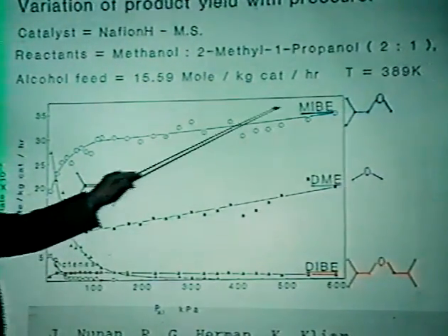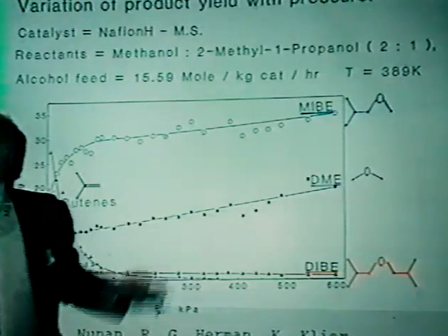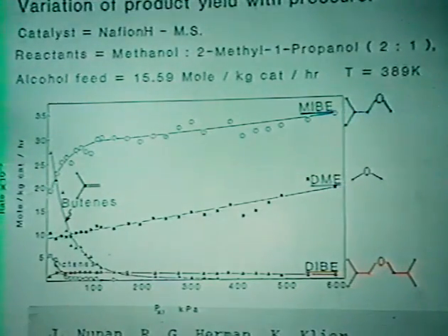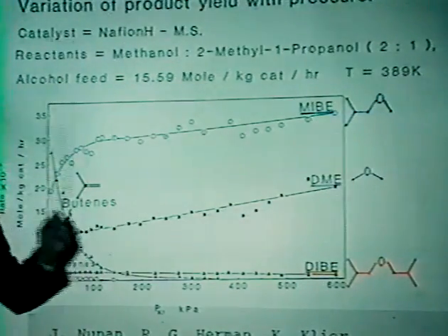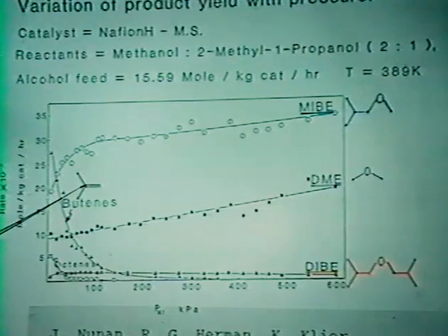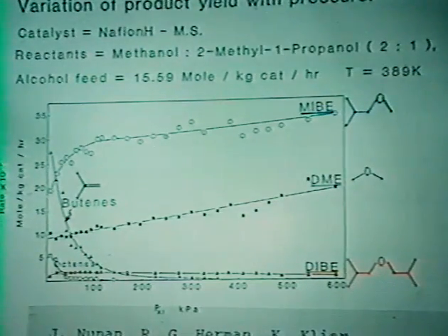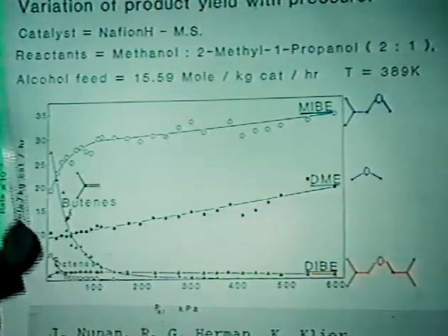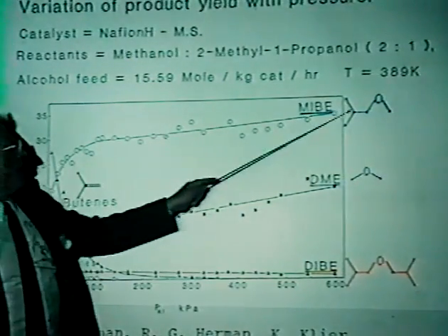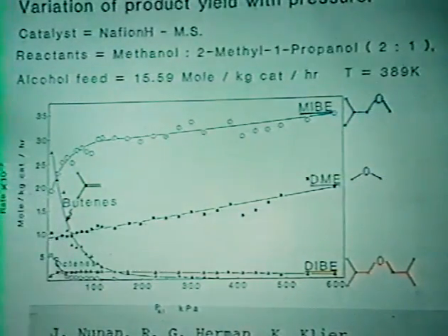The ether is MIBE, methyl isobutyl ether, an isomer of MTBE. So what this tells you is that the formation of MIBE does not go via isobutene, via the usual carbonium ion mechanism. It has to be another mechanism. So you ask yourself a question: what is the mechanism that gives rise to MIBE from the two alcohols that does not involve carbonium ion?